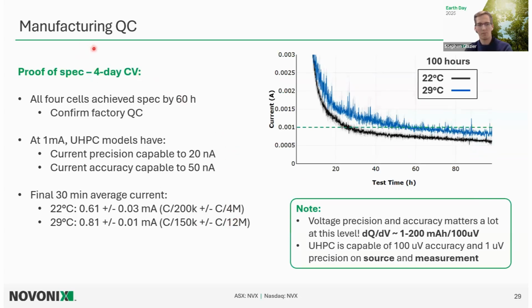So using this constant voltage hold technique, if all the kinetics go away and you can just measure directly the amount of parasitic current affecting the cell, and that self-discharge rate, whether it's just electrochemical or maybe there's something more physical happening within the cell and causing a small amount of self-discharge.